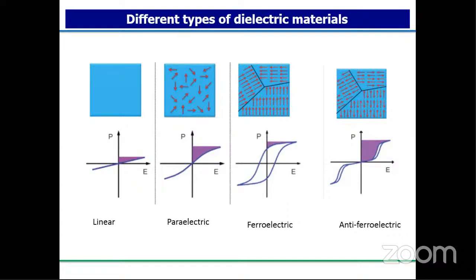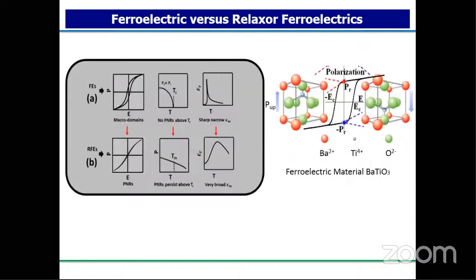For that, I can consider another classification of materials, which we call relaxor materials. If you induce relaxor nature in ferroelectric materials, they are called relaxor ferroelectric materials. What do you mean by relaxor ferroelectric material? Instead of the square hysteresis, we need the slim and slant hysteresis. You observed here, right? A and B are shown in two figures. There we have the square hysteresis. Here we have the slant and slim hysteresis. When you have the slim hysteresis, your energy loss will be less, so you have more efficiency. And here we can increase delta P, because PR is small and P max is high, so that we can improve delta P.